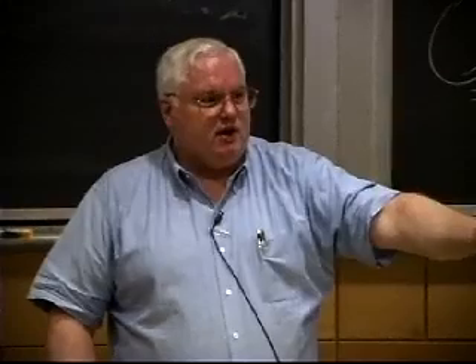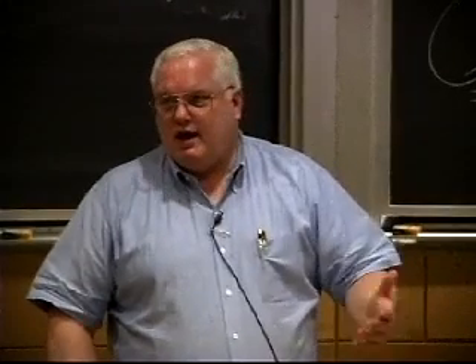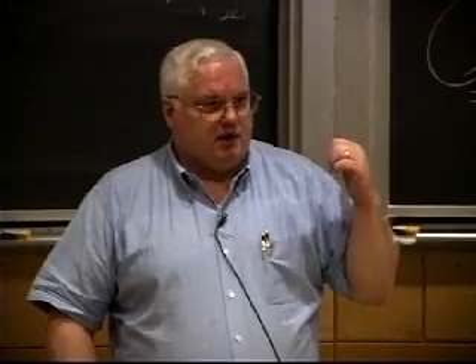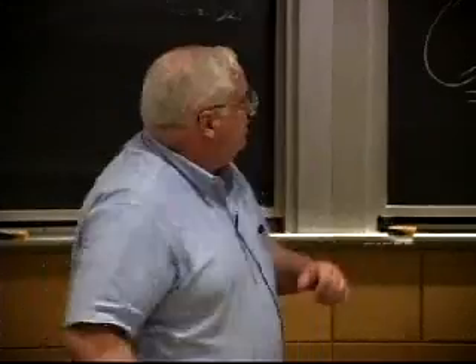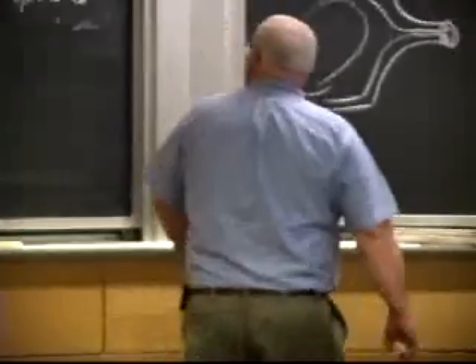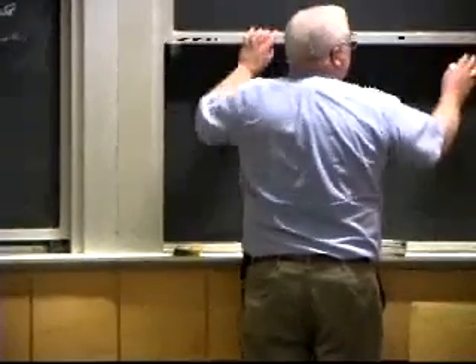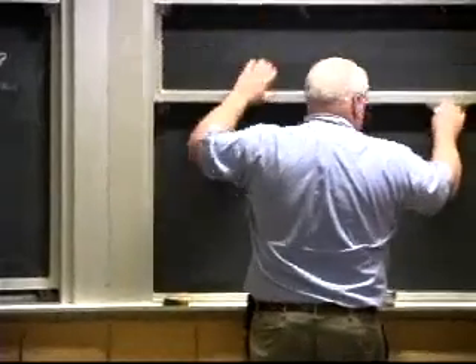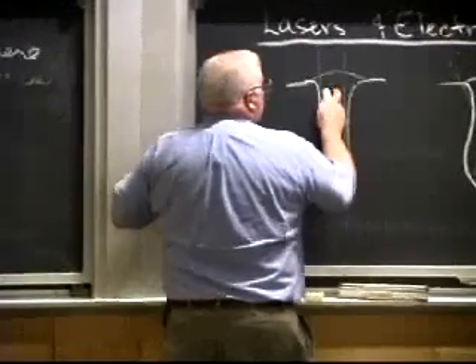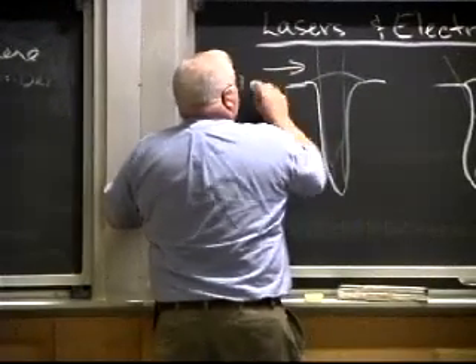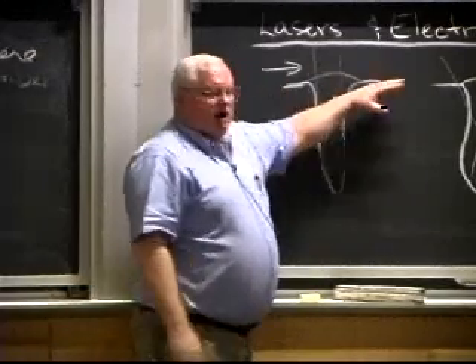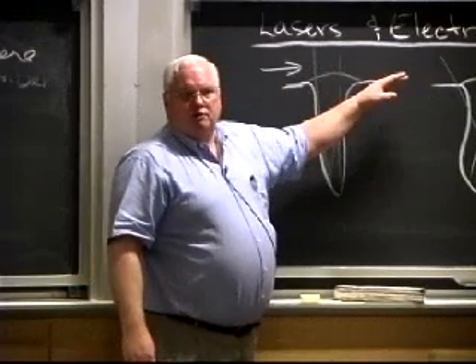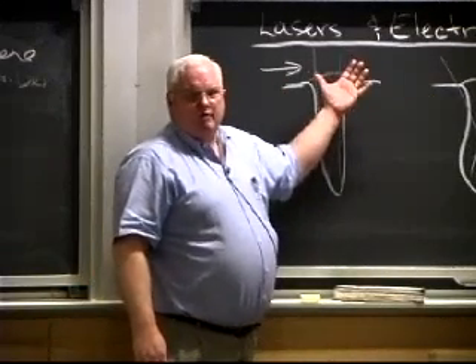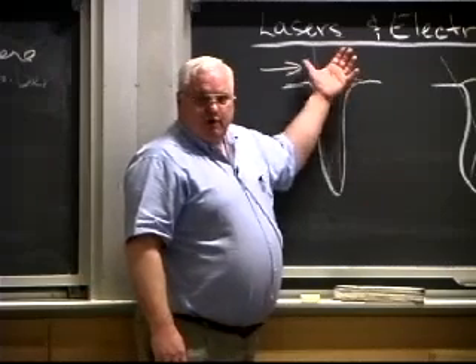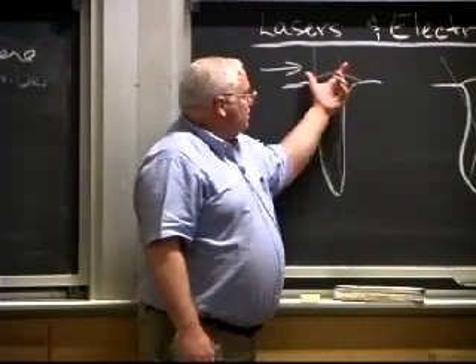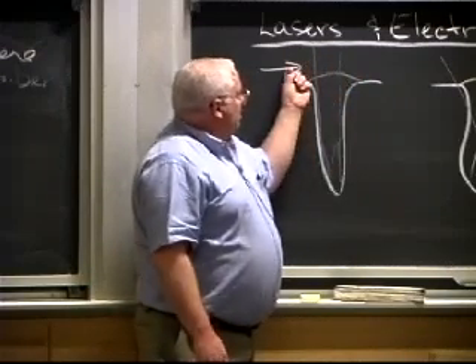A free electron will absorb the light, and the last thing I want to do is generate free electrons. So it turns out you typically, in laser welding, if you're in the United States, you use helium. If you're somewhere else, you might use argon or nitrogen. But you have a transverse gas flow to try to blow aside the metal vapor and keep it from collecting up above here, because the metal vapor above here will defocus the beam that you're trying to get in here.